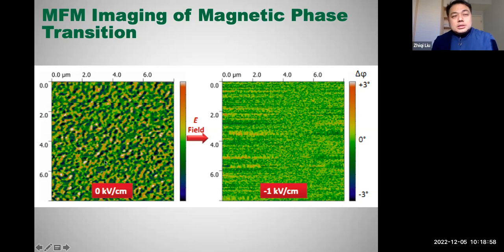At 100 Celsius degree, the iron-rhodium thin film is ferromagnetic at 0 electric field. It has lots of ferromagnetic domains. But when we apply an electric field, this electric field will generate a small piezoelectric strain via the barium titanium oxide substrate. And this strain will be transferred to the top iron-rhodium thin film. Accordingly, all the ferromagnetic domains disappear.